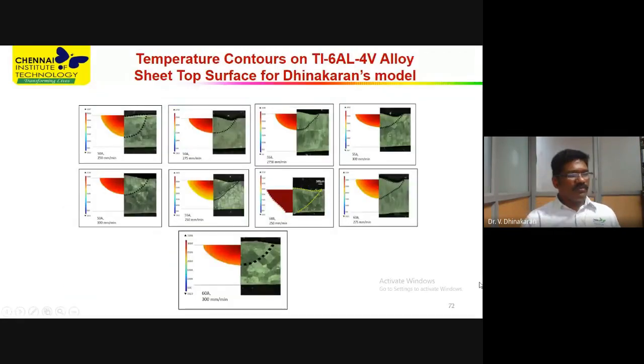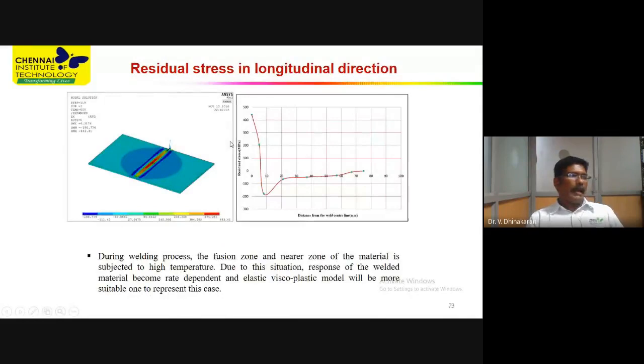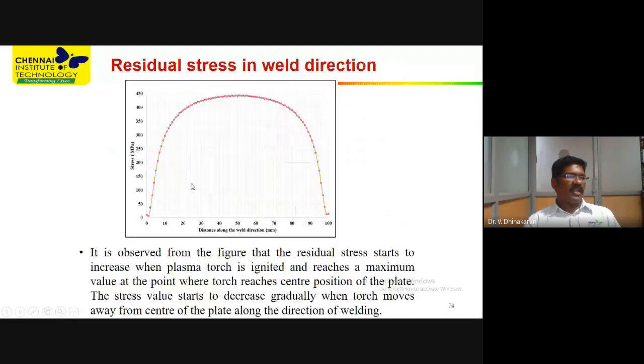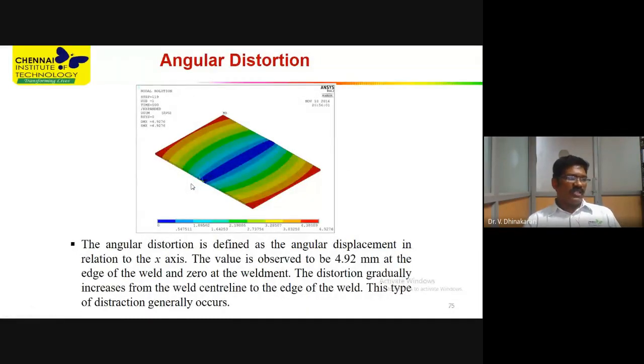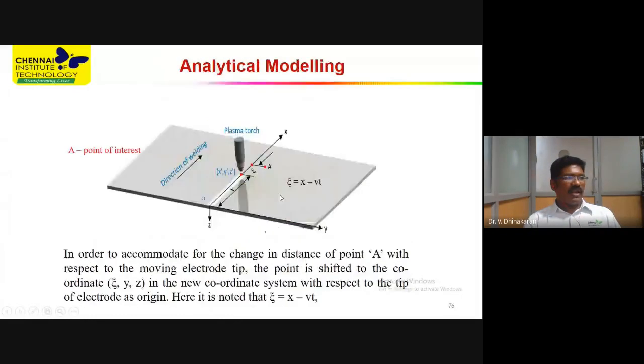Okay, so this is the experimental macrograph obtained from the experiments, and these are the macro profiles predicted from the computational mechanics, and both are almost matching the experimental results. Okay, and we have predicted the stress measurements and angular distortion. The distortion was also predicted by using Dinakaran's model.